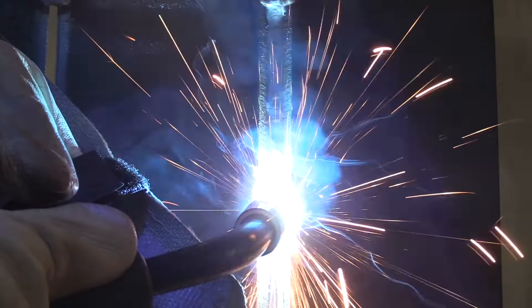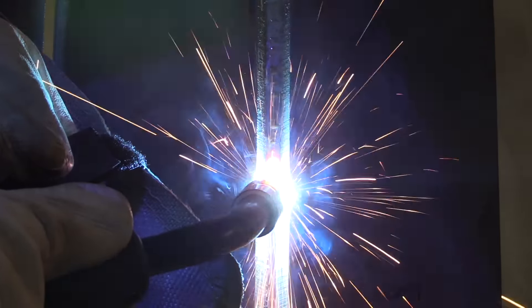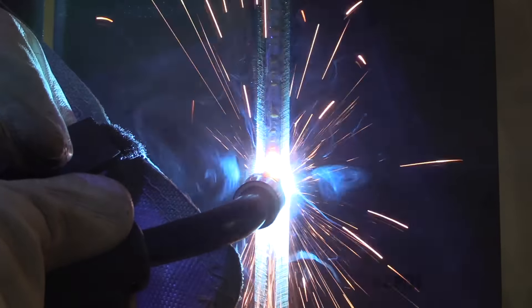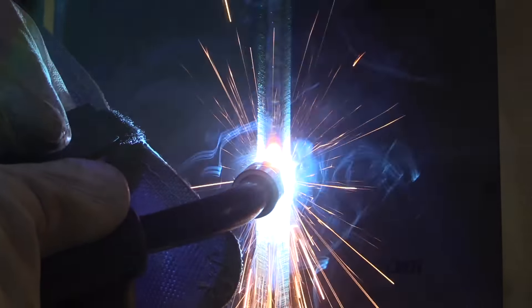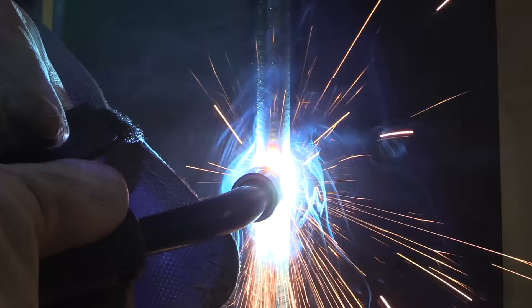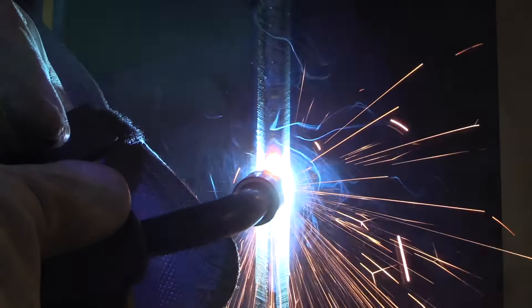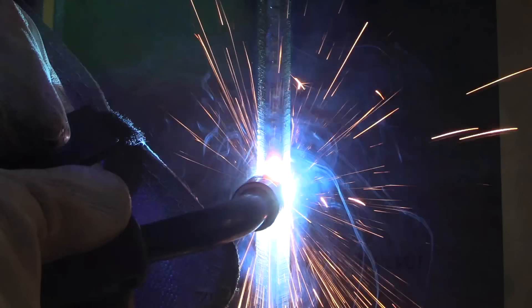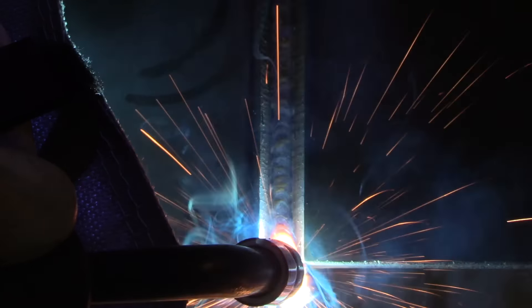So if I don't go very wide at all and keep the wire right on the leading edge of that puddle, right on the edge of it, try to maintain the same gun angle all the way down, maintain the same stick out, don't go very wide, and don't keep the wire so far on the front that you'll shoot wire through and get whiskers on the back side.